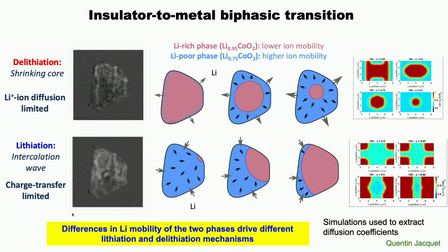So we start off again, we've got this lithium-rich phase. The lithium is stuffed. The lithium isn't going to go anywhere. The diffusion coefficients are very, very low. And then we have a metal insulator transition with an immiscibility gap to form this lithium-poor phase that's metallic, but it's also got much higher ionic transport. And so if you think about your particle, I'm here in my pink phase, lithium isn't moving. I pull the lithiums out from the edges, and it's so much easier to keep on pulling lithium out of the blue phase, and so the particle gradually has this shrinking core.